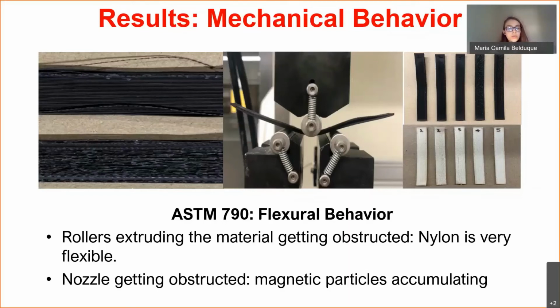This could be attributed to strontium ferrite being accumulated once the nylon 12 is melted again and blocking the nozzle, or decreasing the amount of material being extruded. It is recommended to use a 3D printing temperature of 260 degrees Celsius minimum. An example of some of the defects that we obtained during 3D printing can be seen in the images. Some of the lines of the layers in the final layer are smooth and the remaining layers seem to be incomplete, whereas on the other sample, the entire final layer is in good shape.